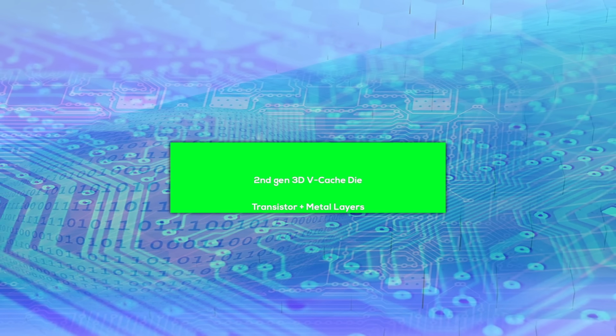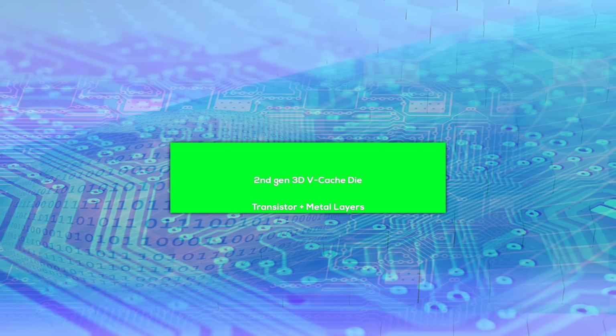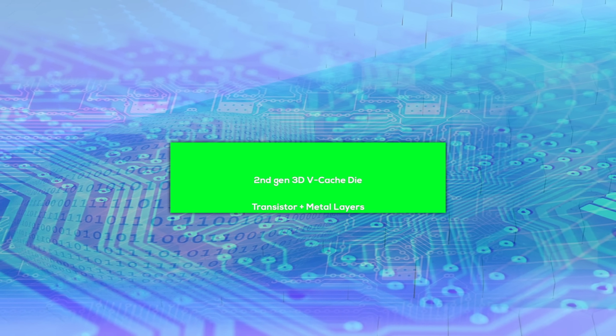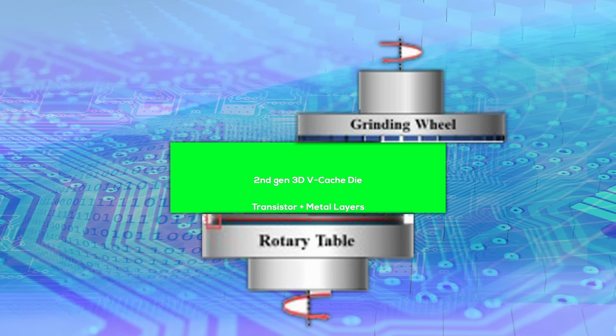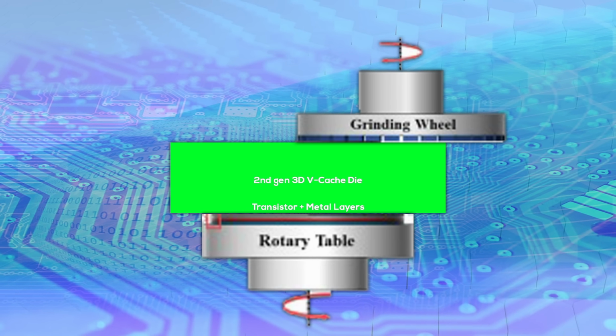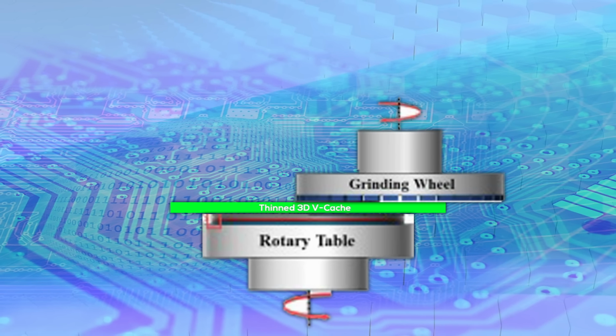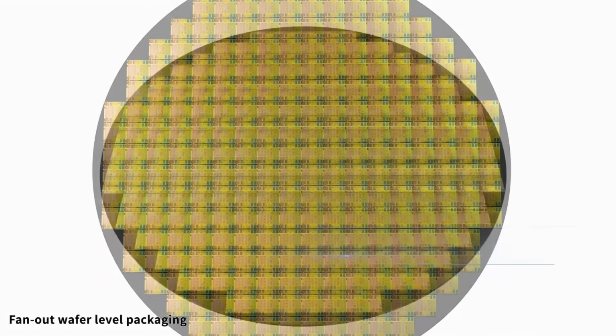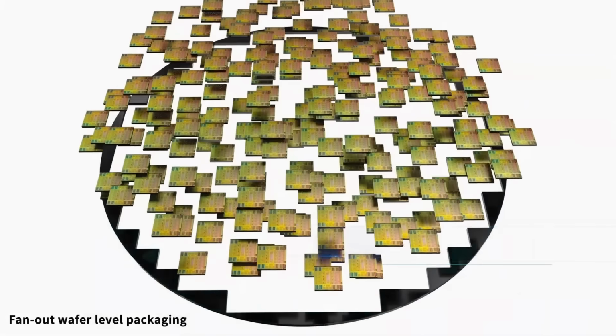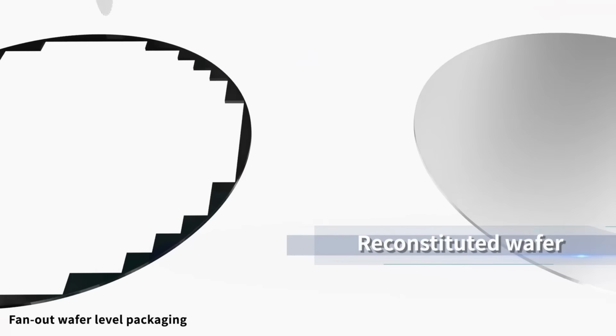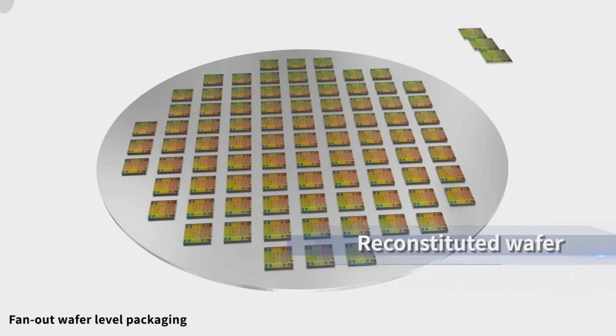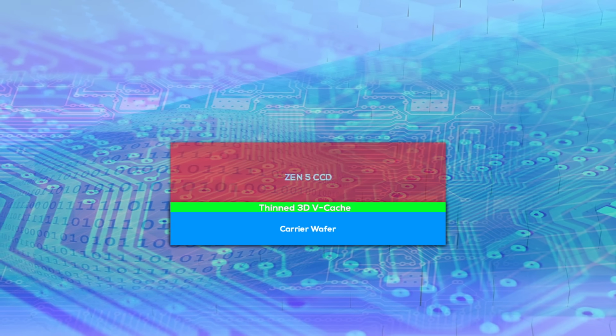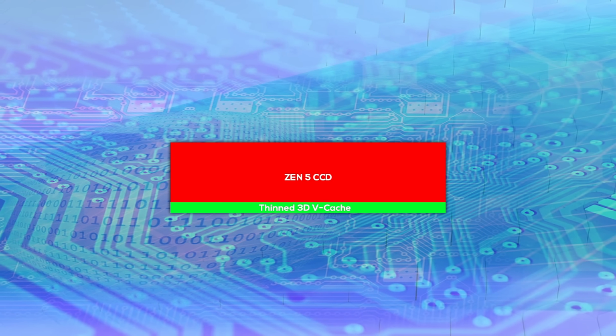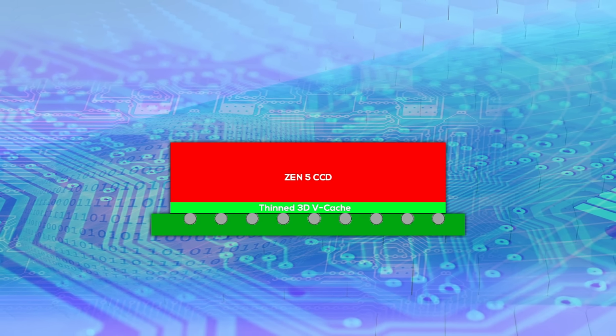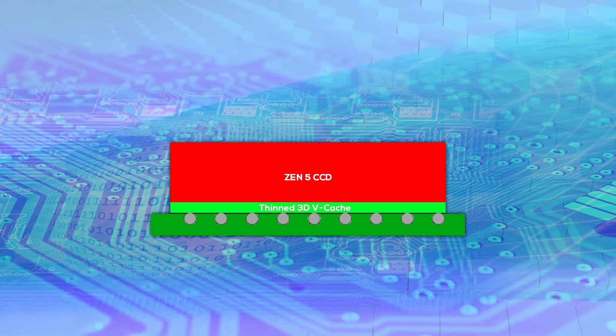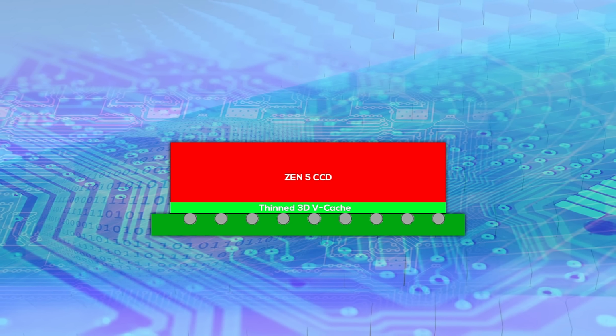The first one is the most straightforward. We start with the new 3D V-cache chiplet. Since it's placed on the bottom now, it has to be thinned down to reveal the hybrid bonding interconnects and TSVs on the backside. So we would take the wafer with the cache chiplets, run it through the wafer thinning process, and then build a reconstituted carrier wafer, which we then bond to a Zen 5 wafer. These Zen 5 CCDs would still require a little bit of thinning because the final product has to be the same height as a standard Zen 5 CCD, and the cache chiplet on the bottom does add a little bit of height. But that would be it.